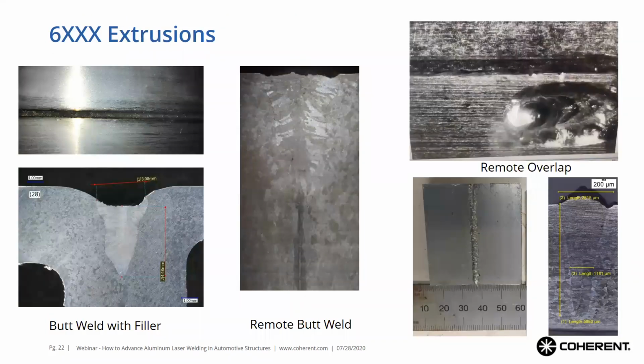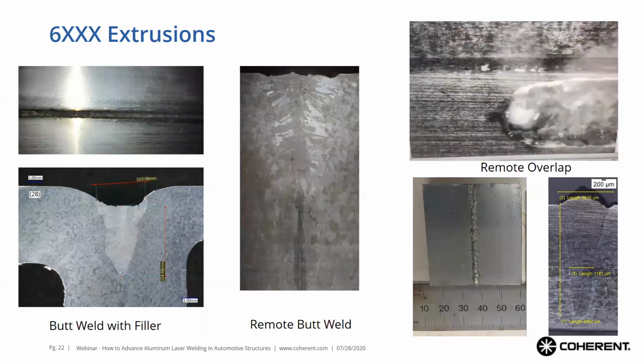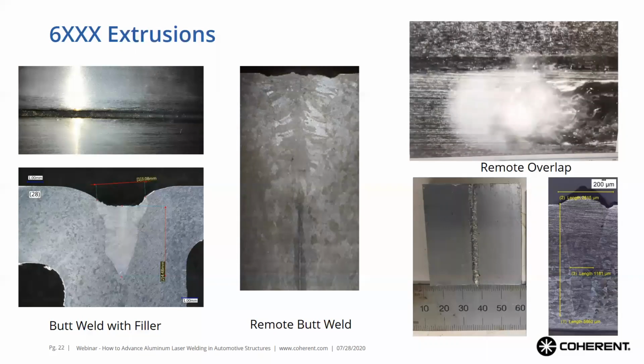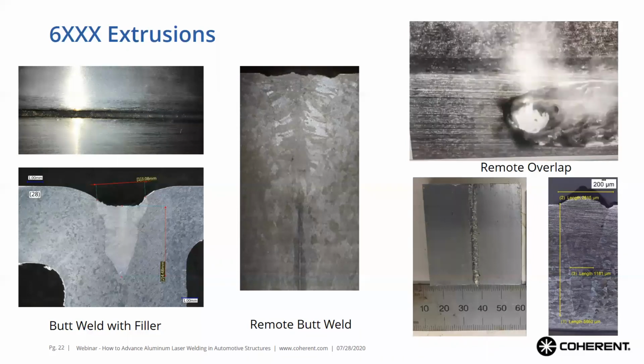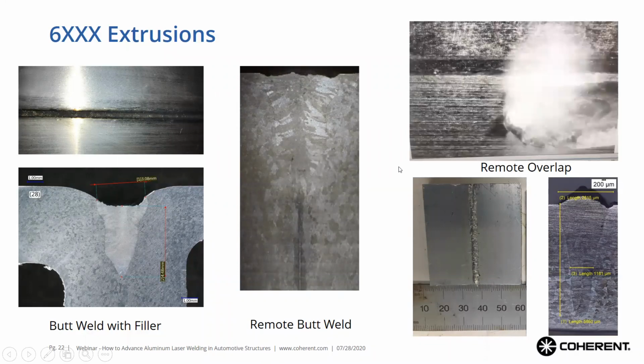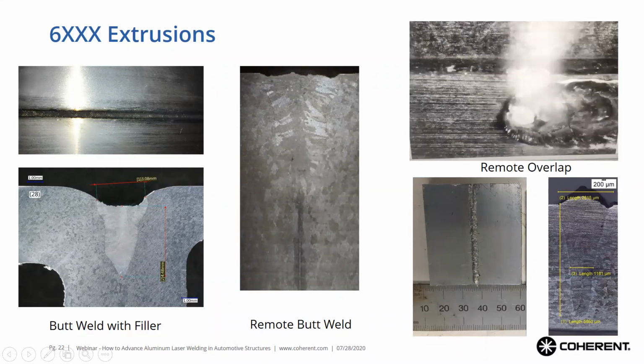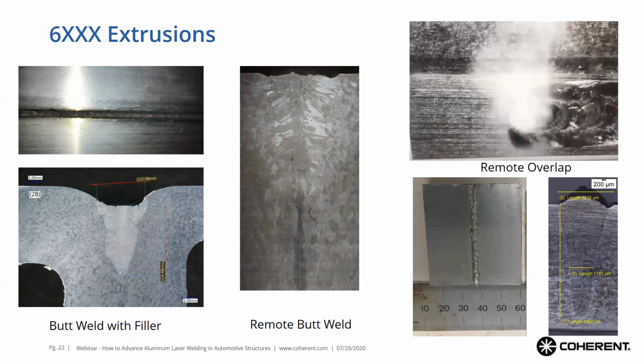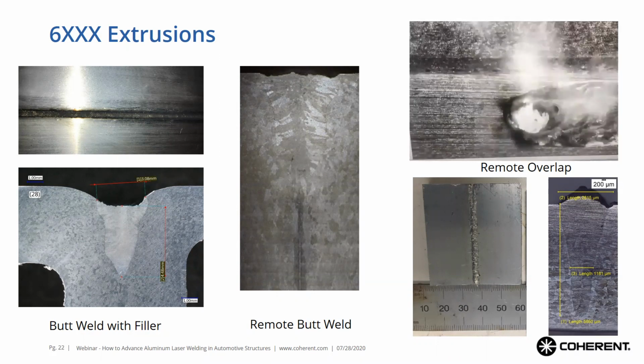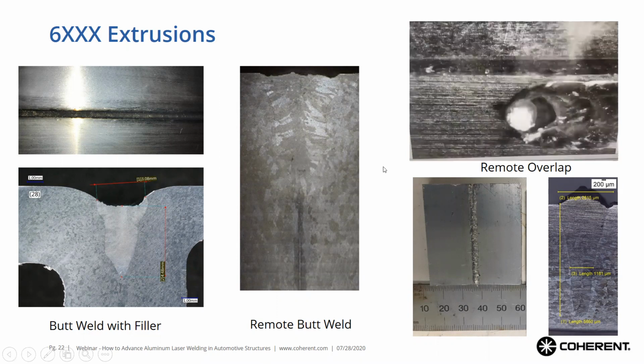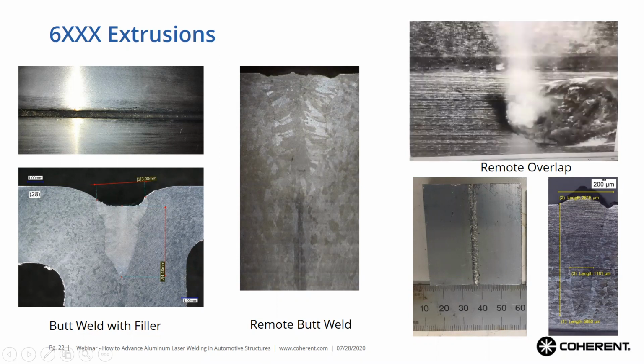There are some examples here in 6000 series extrusions, starting on the left side with a butt weld done with a filler material. In the center area is a butt weld again, done with a remote weld. And then on the right side an overlap weld, done again in 6000. If you look at the high-speed video, you also see that it is a pretty disturbed pool that you typically get on 5000 and 6000 series aluminum.